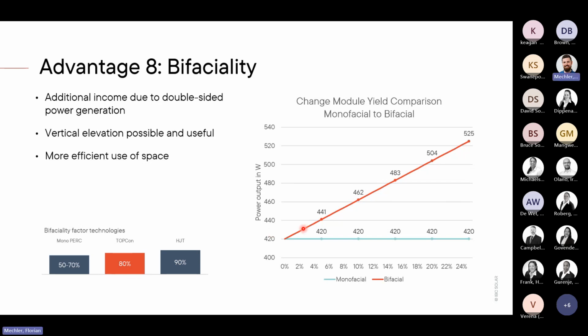What does this mean for producing energy? With a 420 watt module, when you have 6% bifaciality, so 6% comes from the backside, the 420 watt module can produce 441 watts. And we see it can go up to 25%, but it's more or less a theoretical value. You can go up to 525 watts with a 420 watt module. So you get more for the money.